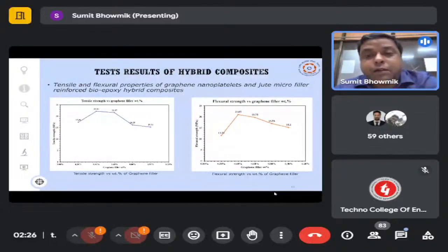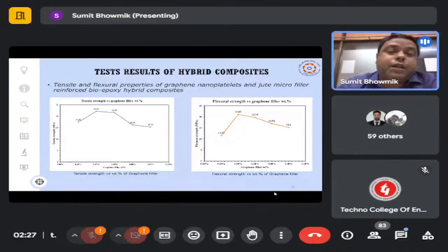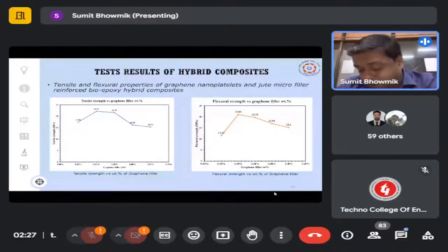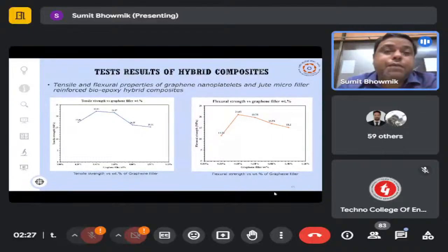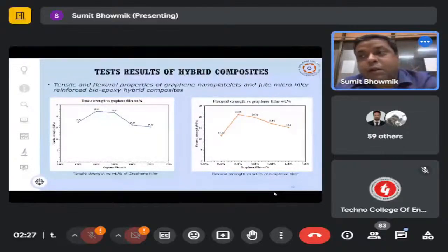So after incorporating graphene nanoplates with jute microfiller, this is the tensile strength. And it has been observed that even with the graphene filler variation, the strength increases up to a certain level. Earlier we varied the filler. Now specifically for jute filler, it has been observed that at 5% filler reinforcement, the material gives the best tensile strength. So 5% filler has been considered for the jute. Now graphene has been incorporated, and the graphene was varied: 0, 0.2, 0.4, 0.6, 0.8, and 1%, 1.2% increases.